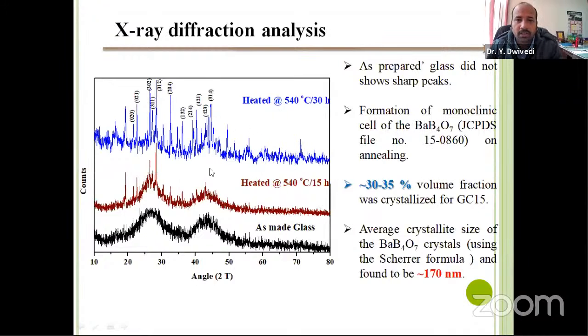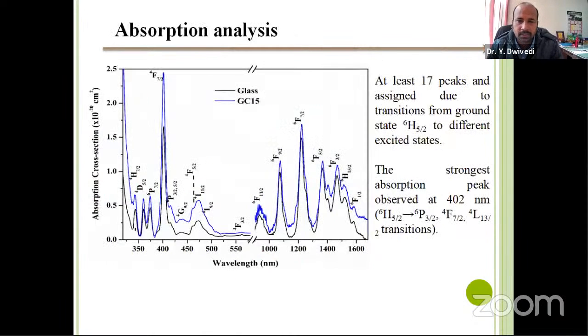If you heat it for 30 hours, you can see lots of crystals are there, but now these crystals are not only barium tetraborate, B4O7 - there are some other impurities, some other crystals also growing there. Approximately 30 to 35% of the volume got crystallized. We also calculate this absorption cross section, and it has lots of these peaks.